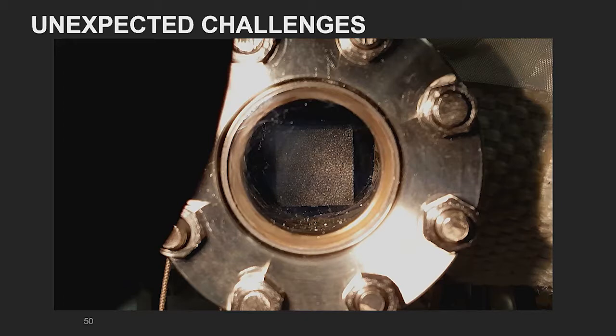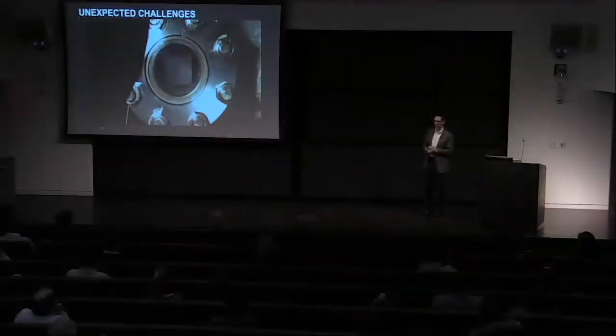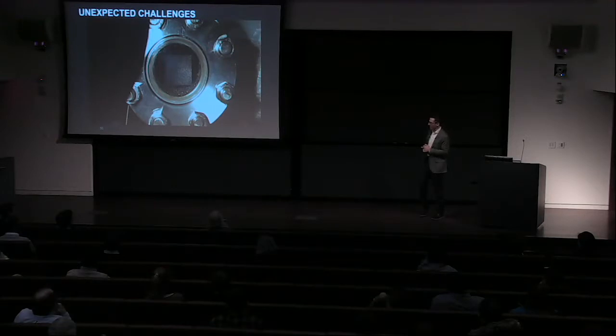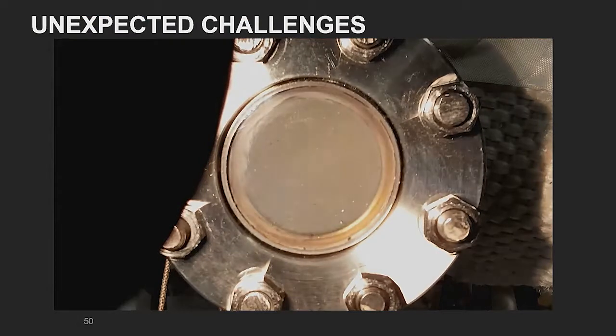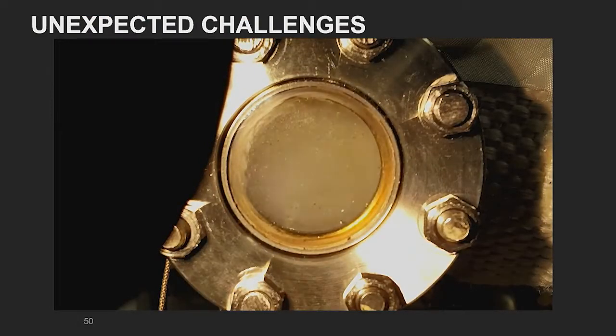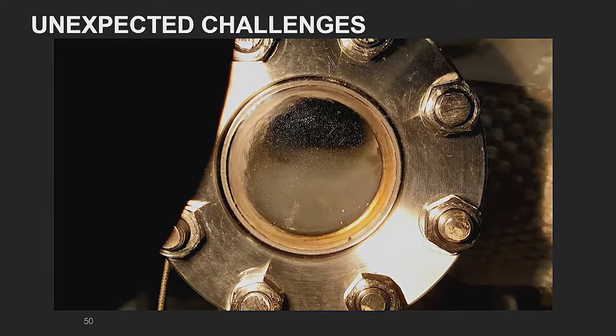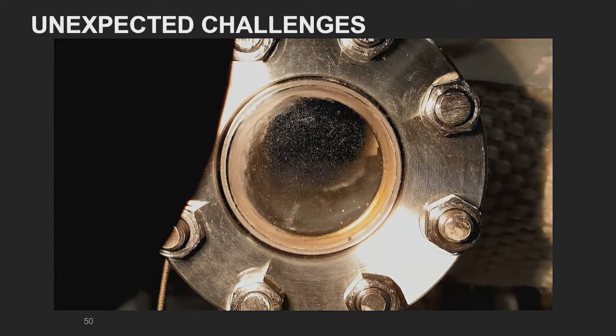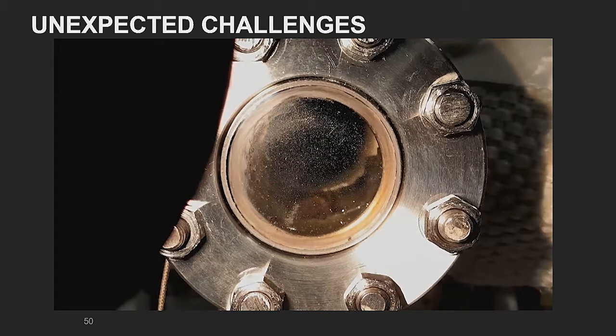So what we did is we positioned them near a port so we could watch what was happening during the reaction. And what you're going to see is a short video here where it has been exposed to precursor A, the trimethyl aluminum, and I don't know, 4 or 5 seconds into the video comes the water pulse. Smoke clears, it's gone. It actually did disappear. So what on earth is going on?